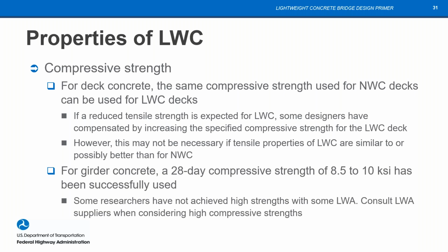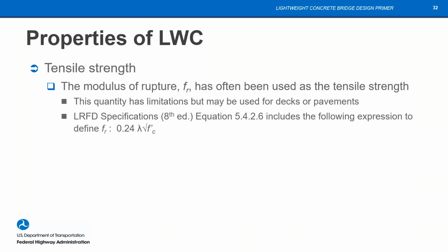For girder concrete, 28-day compressive strength can be used 8 KSI or maybe even up to 10 KSI. And in some cases, this is just a little caution here too. Some researchers have reported that they can't achieve higher strengths with some lightweight aggregates, but sometimes they don't have as good an understanding of how you work with lightweights as some of the suppliers for lightweight aggregate. So I would encourage you all to consult with lightweight suppliers when considering the higher compressive strengths and see what they think about how to achieve that.